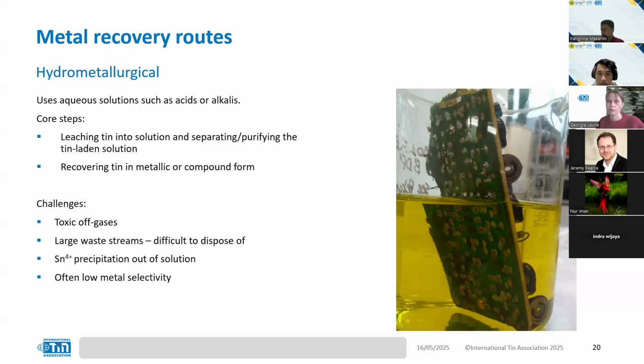Alkaline leaching, on the other hand, uses strong bases to dissolve tin, forming soluble stannate products. One of the main advantages of this over acidic is it's more selective for tin and lead, for example, and can leave behind less soluble metals in alkaline media, such as gold. Again, in this scenario, oxidants can improve the efficiency of alkaline leaching. An example in recent research is using peroxides to enhance the oxidation of tin in alkaline media.